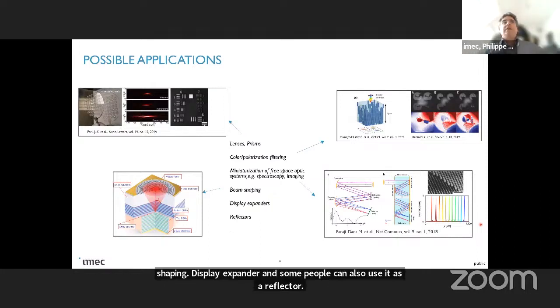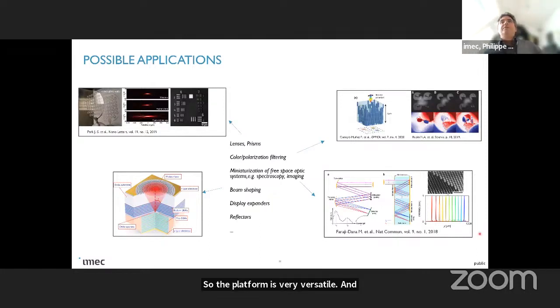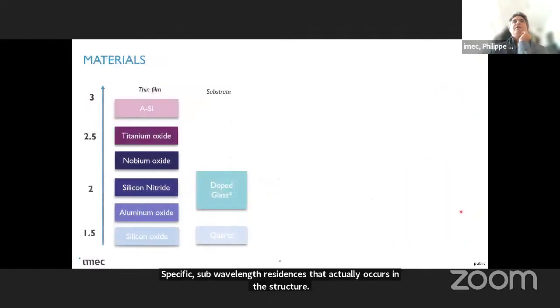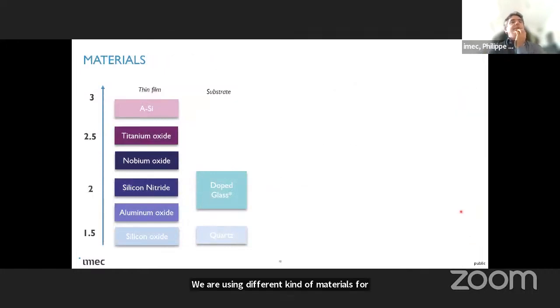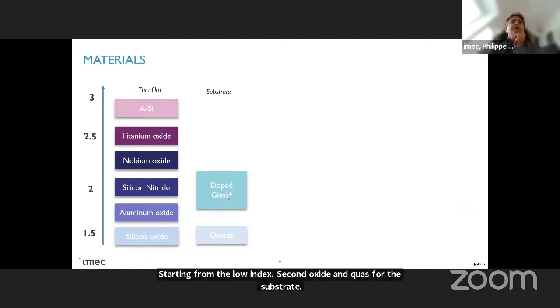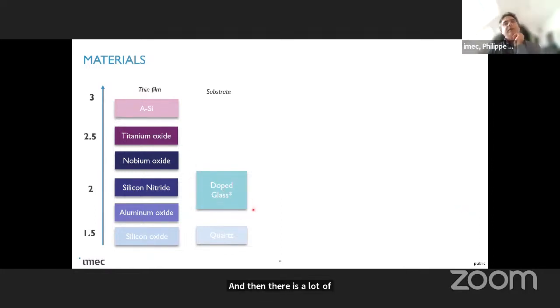And it relies on specific sub-wavelength resonances that actually occur in the structure. We are using different kinds of materials for that, starting from the low index silicon oxide and quartz for the substrate. And then there is a lot of work going on with doped glass, where you're using the core of the glass also as a waveguide. So that is very popular in AR/VR.